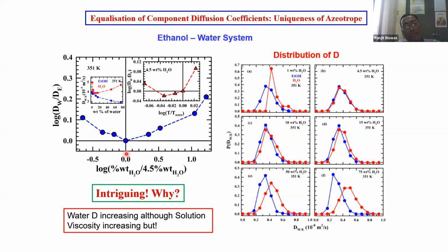This equalization of diffusion coefficients of the components we thought would be a signature, a dynamical signature. And this must be an effect. This cannot be the cause of formation of the azeotrope. So we are trying to find out what is the cause. And this is intriguing. Why intriguing?